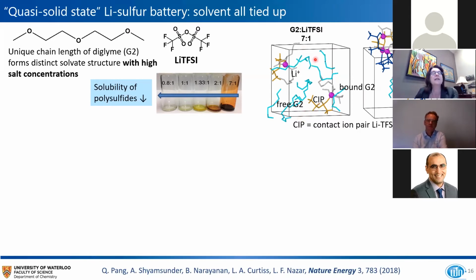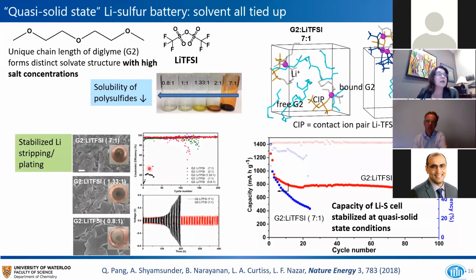And you can see that at the dilute condition, which is here, you have a lot of free diglyme in solution. But when you have a very low ratio, you have the diglyme bound up in the form of these contact ion pairs, effectively forming a nano network of the solvent. And so the diglyme is no longer, as I said, available to dissolve the polysulfides. And moreover, it isn't available to inhibit or to corrode the lithium negative electrode.